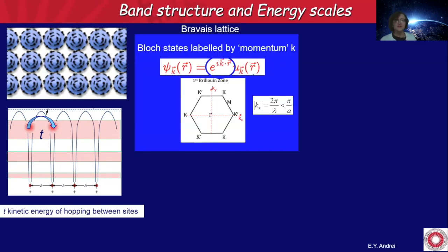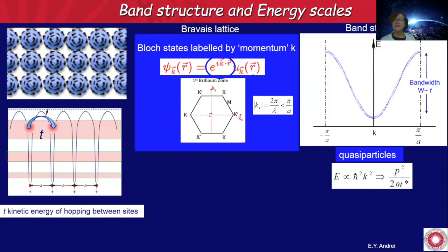Now, there is something very special that happens when you have a so-called Bravais lattice. A Bravais lattice is one where every atom lives exactly in the same neighborhood as every other atom. If that is the case, the electronic wave function is basically a modified plane wave. So the electrons can move freely through this crystal with practically no scattering off the atoms, as long as their wavelength is longer than the interatomic length, in other words, as long as the wave vector lives in what we call the Brillouin zone. In that case, the energy-momentum relation of this electron is simply parabolic.